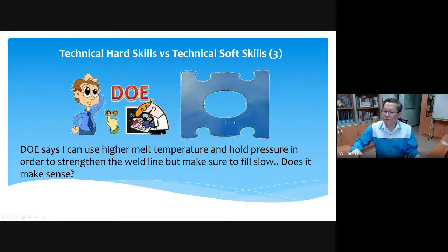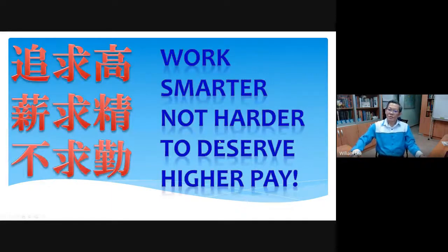Because if you fill the part slow, that means the temperature will cool down. When the temperature cools down, by the time the two melt streams meet each other, you can see a visible weld line, right? So that is to say, you have to again understand the inside of this process in order to choose the right parameters and the right factors. Otherwise, the results will not give you a logical reason. So my advice, therefore, is to work smart and not harder in order to deserve a higher pay.